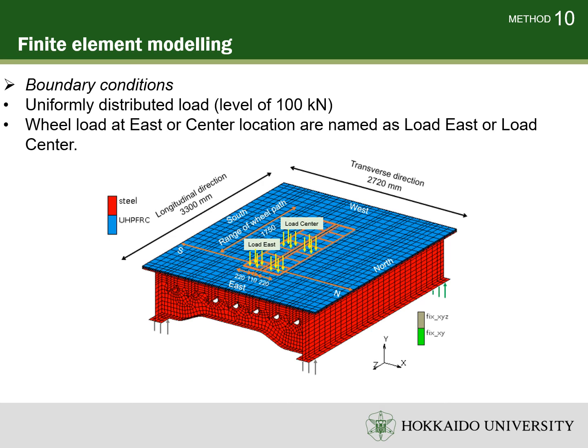For the static analysis, three uniformly distributed loads, which are named as Load West, Load East, and Load Center, as shown in the figures, are located in the loading lane, acting on the area of 220 mm multiplied by 250 mm, which is assumed as the rubber tire contact area. The static load level is assigned to be 100 kN, referring to the experimental design.